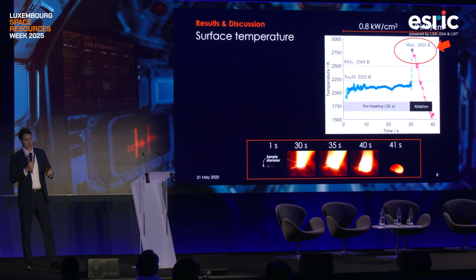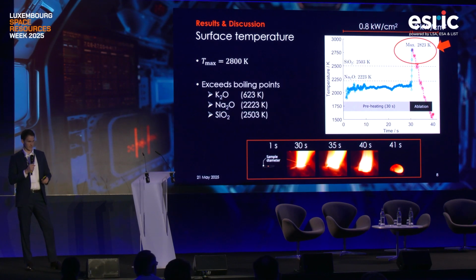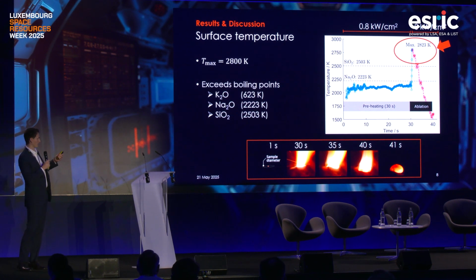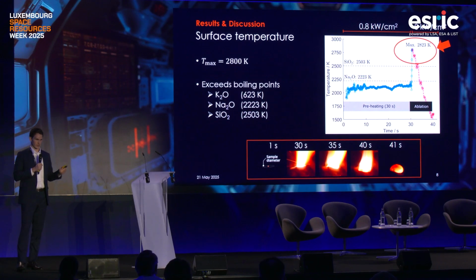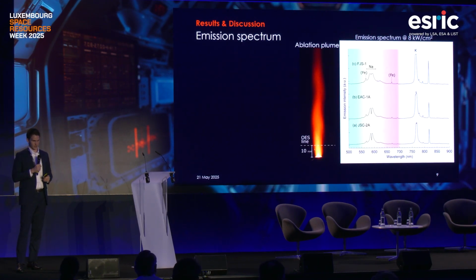For now, what we did is a preheating prior to the large intensity radiation, at 10% of the laser power, to slowly heat the sample and prevent cracking before we utilize the full power. Then we switched on the full laser power, and we reached a temperature of roughly 2,800 Kelvin. Some images you can see here during the process at 30 seconds illustrate this 2,800 Kelvin point. This exceeds some of the boiling points in the table that we saw earlier. So naturally, we would assume that at least these species are present in this plume that we see in the pictures. And we do see that partly in the emission spectrum that we measured here 10 millimeter above the surface.